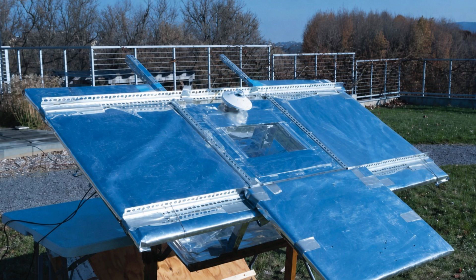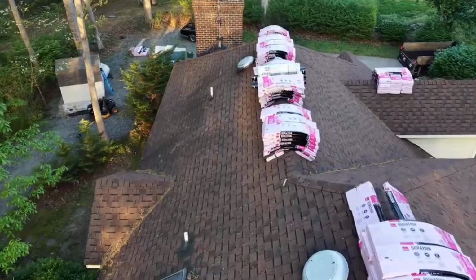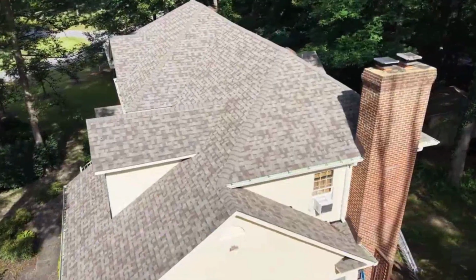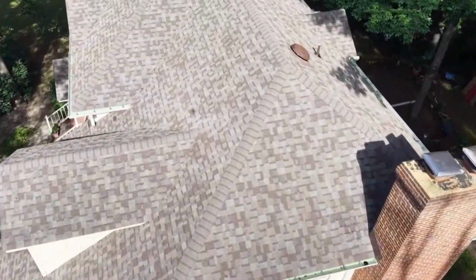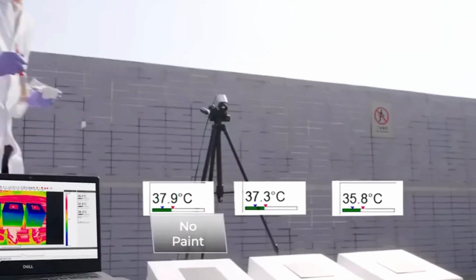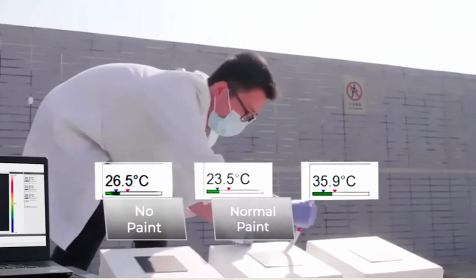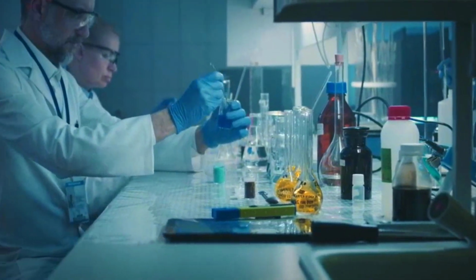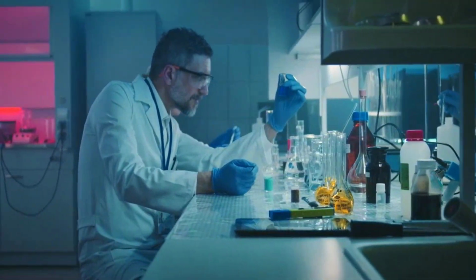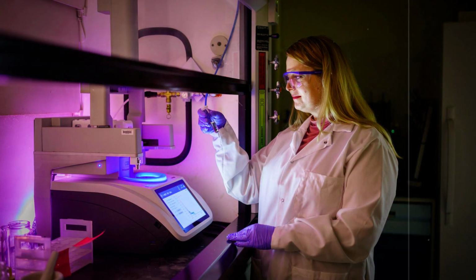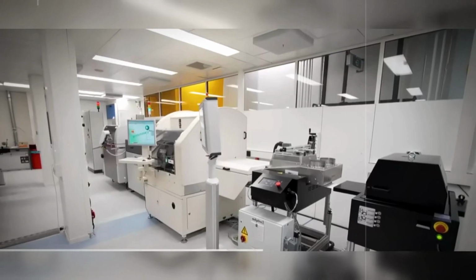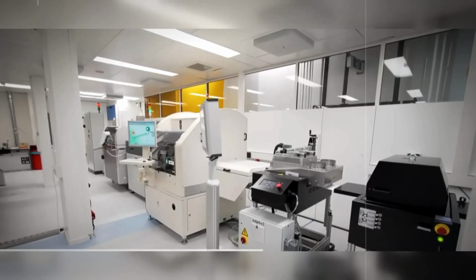During testing, the surface reportedly reached nearly 5 degrees Celsius below ambient temperature around solar noon. The important discovery was not that every homeowner should reproduce that exact multi-layer structure. It was the demonstration that passive radiative cooling could continue functioning during daylight when the material was properly designed. That result encouraged other researchers to search for materials that could be produced more cheaply.